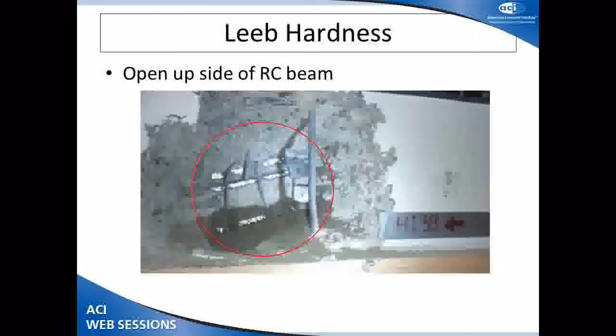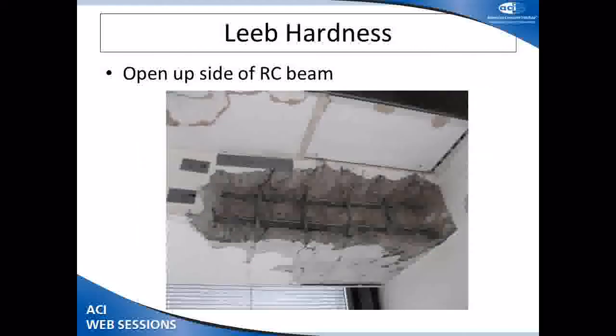Okay, just some shots. What the technicians do is they take the cover concrete off, and they prepare the surface of the bars we're interested in to do the Leeb hardness test, which is a bouncing steel ball. Change of velocity is an indication on the rebound of what the hardness is. The technicians are very careful not to use heat because that changes the metallurgy. They do the preparation with light sandpaper. That's just another shot in a plastic hinge in the Price Waterhouse building, one of our second tallest concrete buildings in Christchurch. That's about to be demolished.